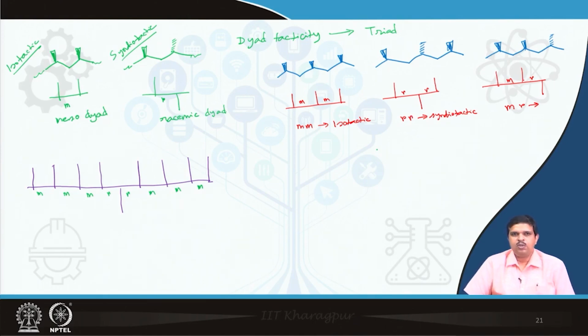So, in one case the catalyst is chiral and it will induce the stereocenter. In the other case, chain end control, the catalyst is not chiral, it is achiral, but you are getting the stereocenter. This is very funny.